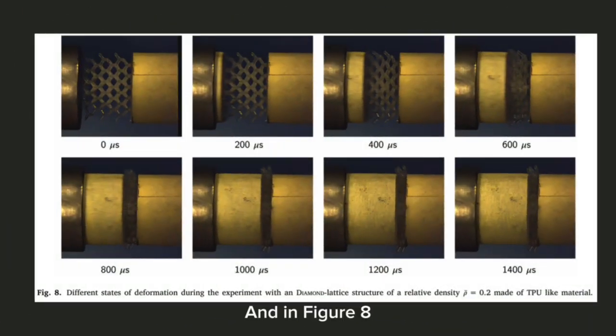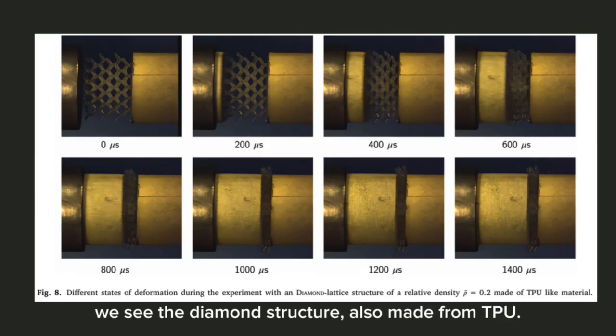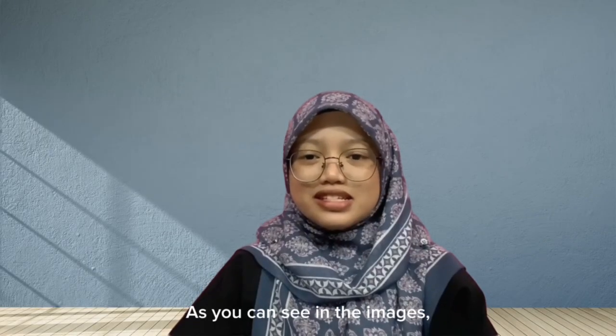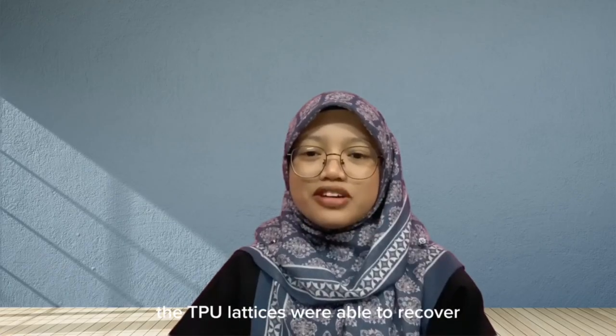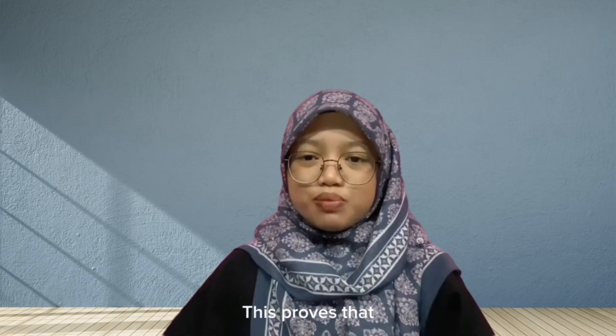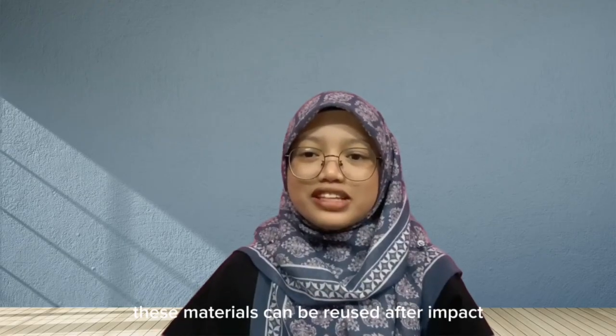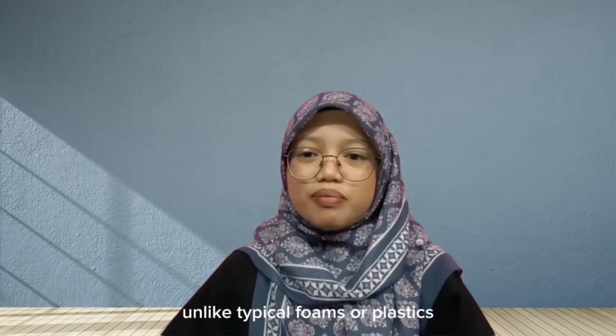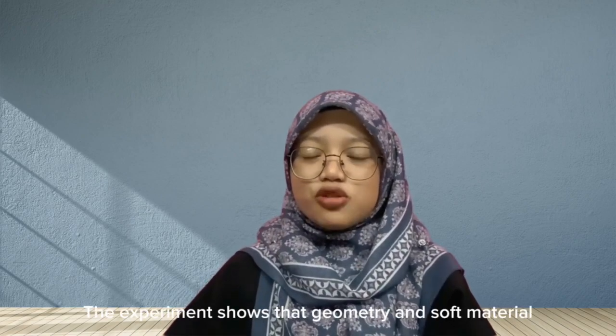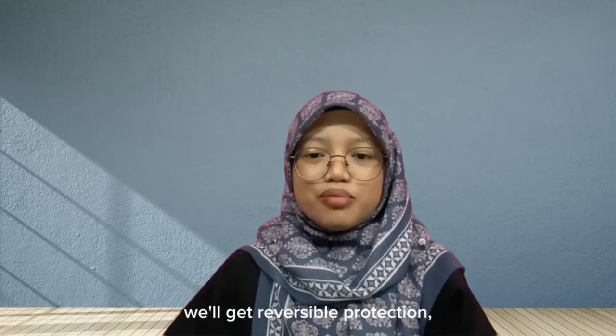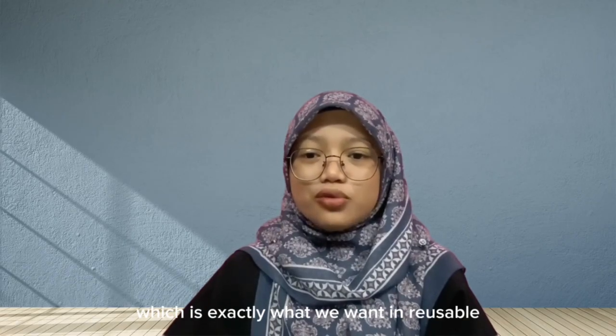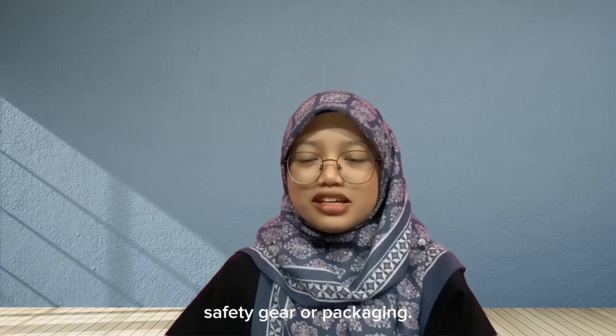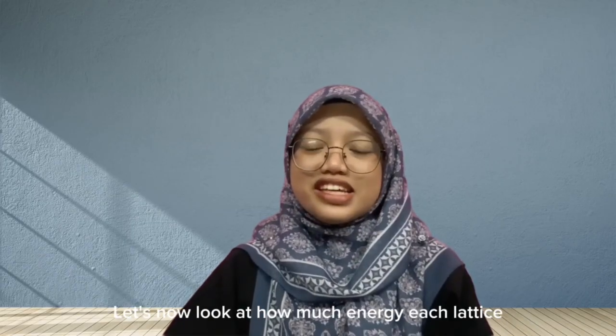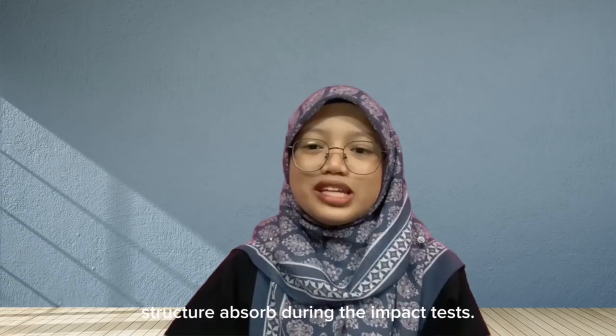And in figure 8, we see the diamond structure, also made from TPU. As you can see in the images, even after being heavily compressed, the TPU lattices were able to recover almost fully to their original shape. This proves that these materials can be reused after impact, unlike typical foams or plastics that break or stay deformed. The experiment shows that geometry and soft materials give reversible protection, which is exactly what we want in reusable safety gear or packaging. Let's now look at how much energy each lattice structure absorbed during the impact test.